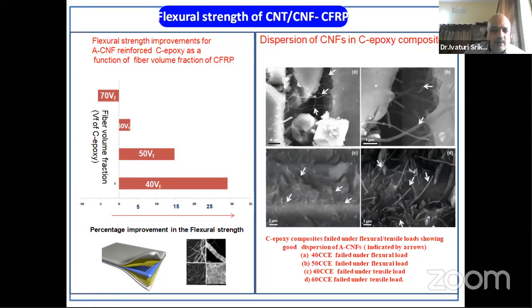But again, our own experiment shows that people, even IIT Delhi, some IITs, have reported 30-40% improvement with the addition of CNTs. But when we interacted, they ignored a few points. Our first point is, they are not aware of the significance of fiber volume fraction. What they have done, they have taken regular carbon epoxy, added CNTs to it, and then reported an improvement of around 25 to 30%. But they used probably a very low VF, fiber volume fraction, meaning matrix is 60%, fiber is only 40%, 40 VF, that is called 40 fiber volume fraction of the composite.